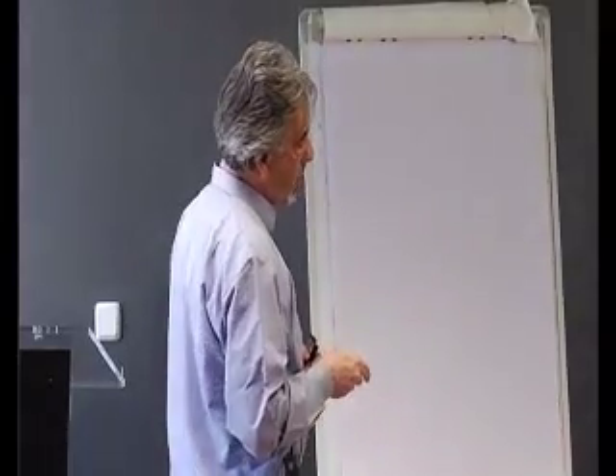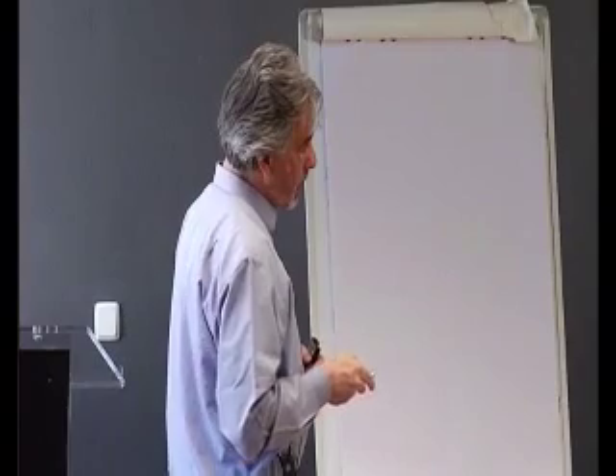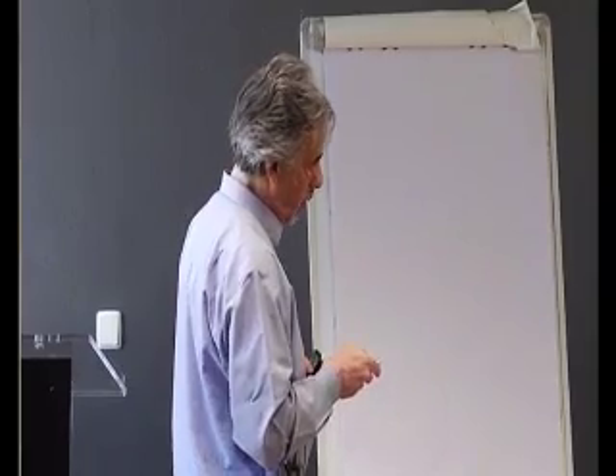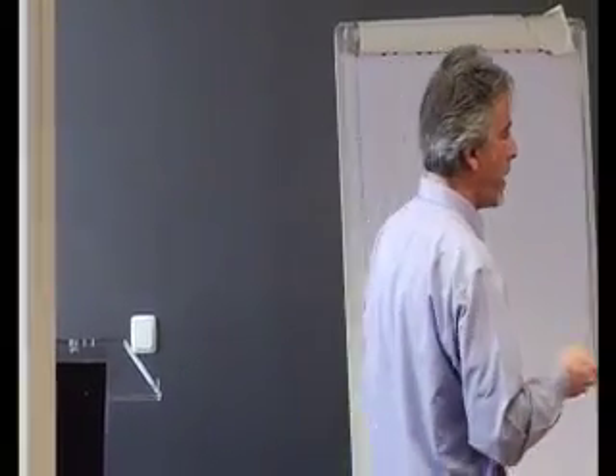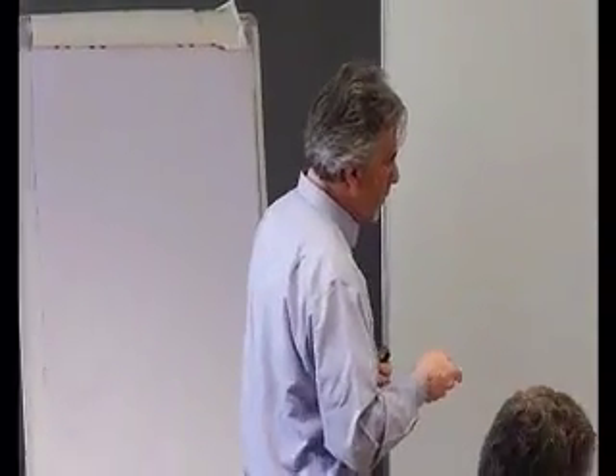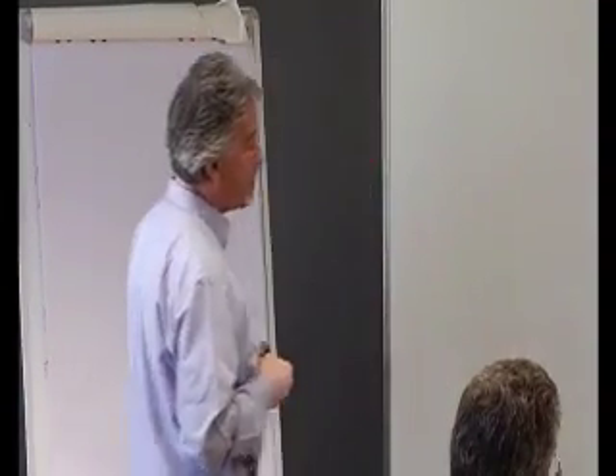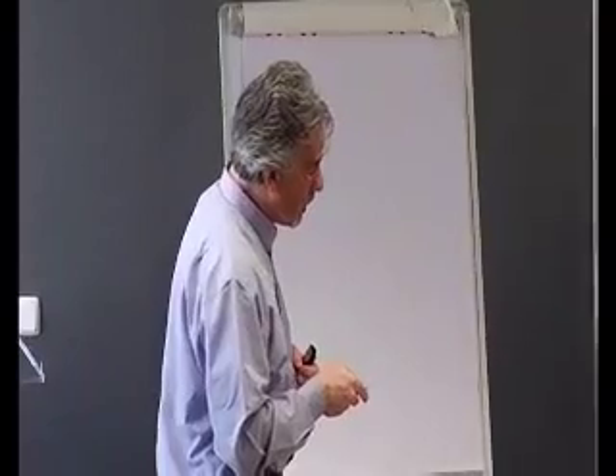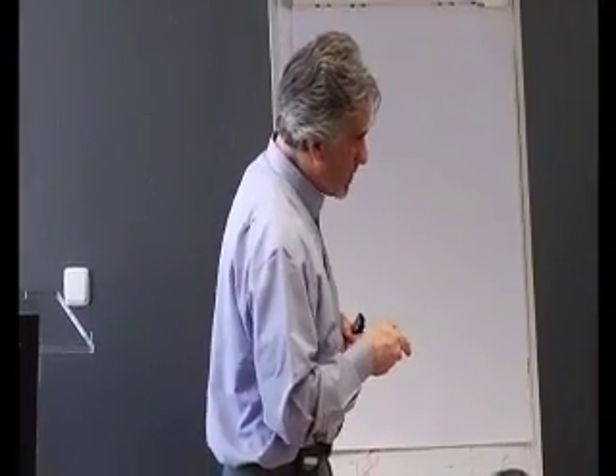This is the fluidized bed being developed in the group of Kodama in Japan. They use nickel ferrites. This is a cavity reactor developed by the group of Al Weimer at the University of Colorado, also with nickel ferrite, so a cavity containing an array of tubes that are packed with nickel ferrites. And this is the reactor that is being studied in CNRS, in Odeillo. They have the reactants directly exposed to solar energy. They are studying the zinc oxide cycle, as we do in Switzerland, and also the tin oxide cycle.